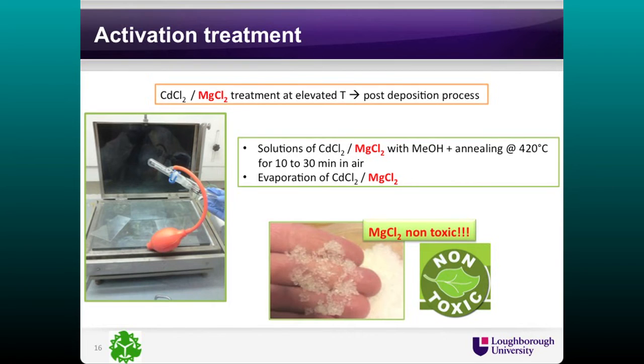But in order to make this device a proper working device, we need an activation treatment. Nowadays, cadmium chloride is usually used as a post-deposition process by solution or evaporation. But we know that cadmium is a toxic material, so our challenge now is to replace this toxic material with magnesium chloride, which is a non-toxic one. And now my colleague will explain to you, in particular, the activation treatment, which is based.